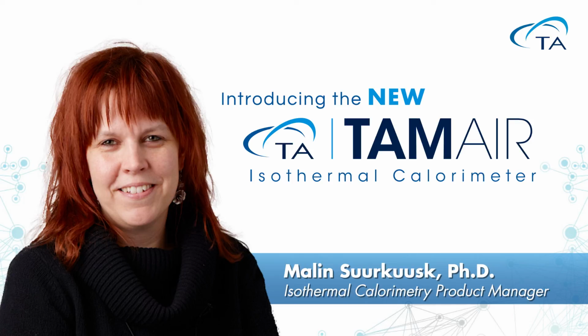The first question that came in was about baseline stability. It asked how critical baseline stability is to testing environmental samples. Baseline stability is critical because over time, if you're going to do an integration and see how much heat is produced, you don't want the baseline to drift away, so you integrate from the wrong starting point or end point during the measurement. Samples can be run for several days to measure what's going on in an environmental sample with microorganisms growing. And if you're integrating this, you would like to know that your baseline actually is where you think it is, otherwise you will get a completely wrong number.